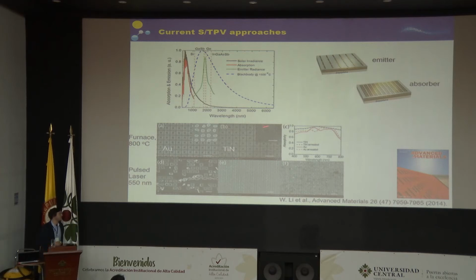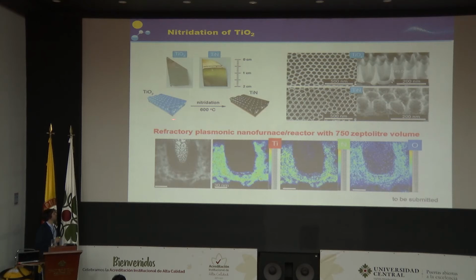Of course, these nice metamaterials, with nice properties and nice arrangements of nanostructures, are usually produced by beam lithography, a method which allows producing microscale patterns. So this is really not convenient if you want to produce solar thermal technology on a massive scale, on a square meter scale. Therefore, we thought to start from a titanium oxide nanostructure and nitridize this structure to titanium nitride.